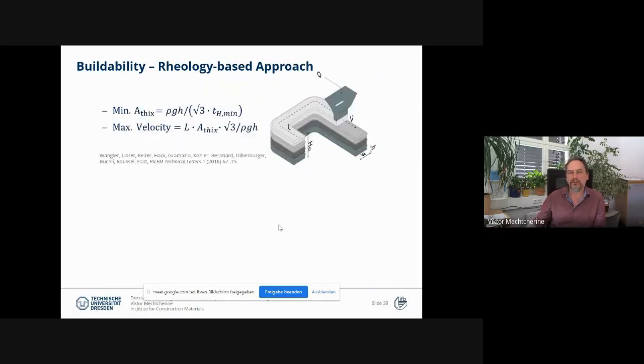However, these tests are not straightforward. I will come right away to this. But what is important, when we have this parameter, we also can shape the process on this base, and you see we, for example, can predict maximum velocity we can afford in the printing process without the structure collapsing. Or if we have some particular understanding about the desired minimum time intervals between the layers, we can actually calculate which rate of the development of the yield stress, so which thixotropy, should be provided by the concrete composition. And we can use, of course, different approaches to steer the thixotropy of the print material.